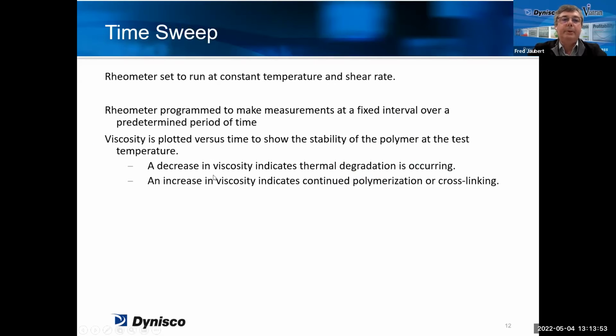The second type of test we can run is called the time sweep test. So basically, our stabilization test, where we are running at a constant temperature and a constant shear rate. So in this case, we are doing measurements at fixed intervals during a predetermined period of time. So we are making a test, stopping the instrument, then starting the piston again, and then taking a second measurement, and so on every minute, or every 5 minutes, 10 minutes. And depending on what the curve is going to do, we will see if we have thermal degradation or if we have cross-linking in the polymers.